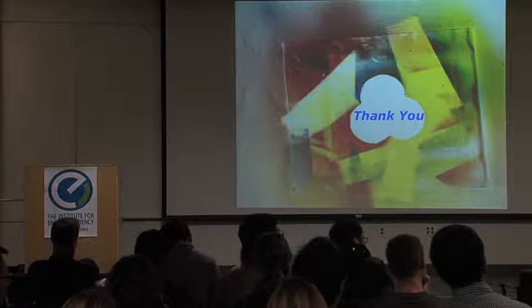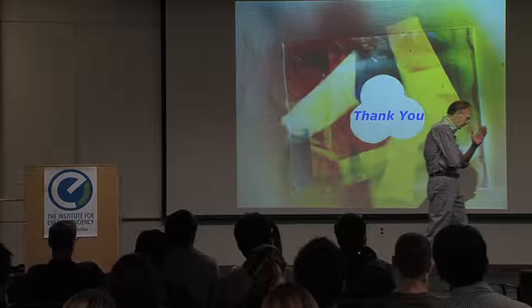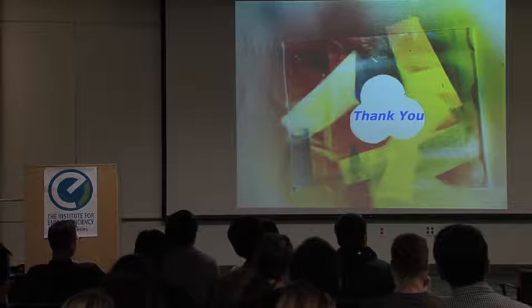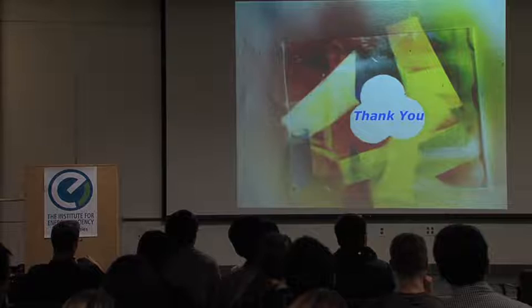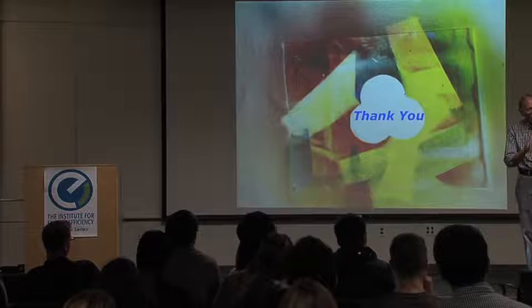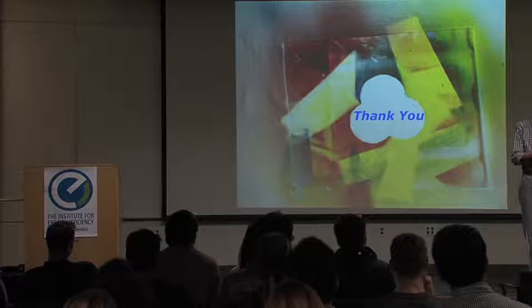Yeah, that's a very good question. Switching time is a function of the electrode and the device. If we're looking at an electrode for a certain switching time, we would mainly use that to compare between systems in the same situation. If we're looking at it in a device, then it is the potential of the real application of that device. For example, with that movie that I showed you, I think that if we wanted to make a display that had multiple pixels on it, and we were going to drive each pixel separately, then in the 10 to 50 millisecond range, we could drive those pixels fully. But I don't think we're going to get to a microsecond.